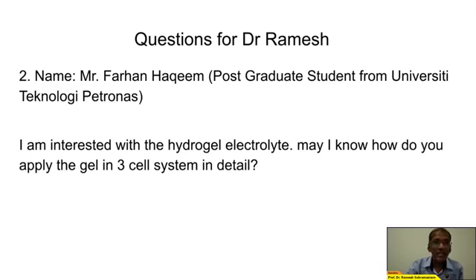So how do we make the hydrogel become a hydrogel electrolyte? Because hydrogel is generally used in biological applications. The main thing for us to produce a hydrogel electrolyte is the incorporation of charge carriers. To prepare the hydrogel electrolytes, we need the host polymer and we need an appropriate initiator, for example, ammonium persulfate. We also need to incorporate a cross-linking agent, which in many cases is a clay. In our lab, we use sodium montmorillonite. And to make the hydrogel become a hydrogel electrolyte, we use a lithium salt or even magnesium salt or aluminum salt, and even ammonium salt can also be used. Once they become a hydrogel electrolyte, then only we characterize.